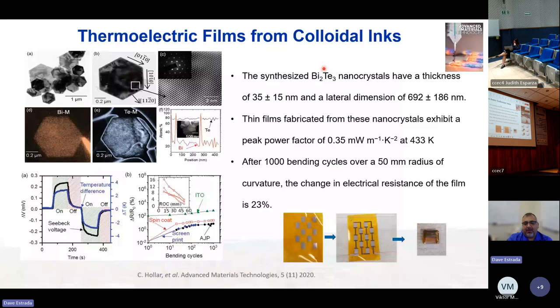So we did some TEM analysis to look at the crystallinity of the flakes, and we have the AFM data, but here we can see the single atoms showing good crystalline nature, good diffraction of these flakes. We did EDS mapping to show the elemental distribution of bismuth and tellurium. We have nice even distribution with the right 2-to-3 ratio. And then we did some thin film fabrication through spin coating and aerosol jet printing to show that we can get good temperature sensing or heat harvesting from these devices.